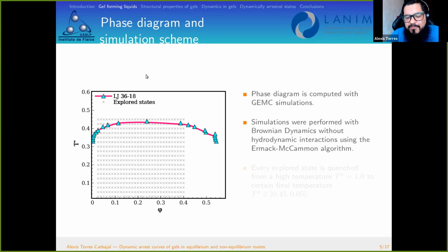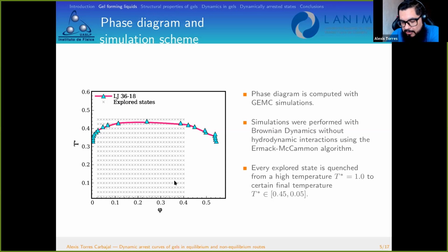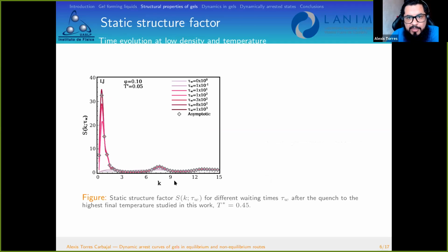And in our simulations, we start with a thermodynamic condition far above the critical point. Then we perform a quench to a final temperature inside the coexistence region of the liquid-vapor zones, in order to see what happens with the structural and dynamical properties. So we explore several thermodynamic states for both models, and the results that we determine are basically structural and dynamical properties.